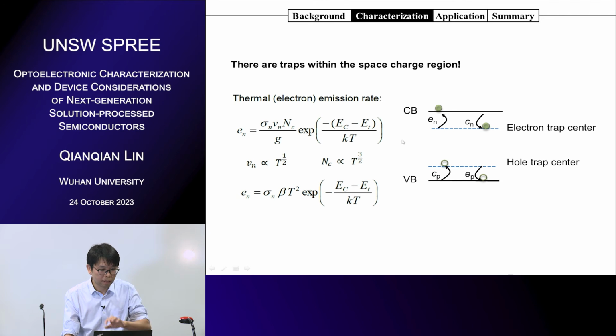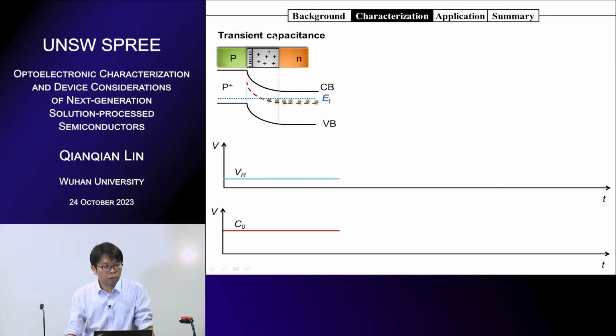So keep in mind that the emission of the carriers is dependent on time and temperature. So we look at the transient of the capacitance measurements. We also have the p+n junction, and all the carriers will be trapped by the trap states because they are deep, below the Fermi level. Here are all filled with carriers, but you have band bending in the space charge region, so the trap states will be higher than the Fermi level, and cannot be filled within this region.